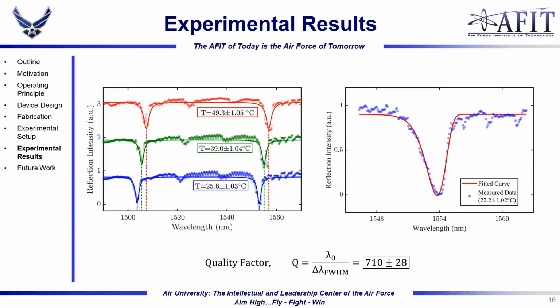to 1580 nanometers. The laser exhibited a wavelength-dependent power output, which is subtracted from each measurement. Each reading then shows a voltage proportional to the reflected power over the spectrum introduced by the variable wavelength laser. Measurements are then normalized between 1 and 0. The graphic on the left depicts 3 such measurements, with the area distribution plotted on top of the data for visualization purposes only. The area distribution was not fit to the individual dips because they exhibited a non-ideal asymmetry, as seen in the figure on the right.